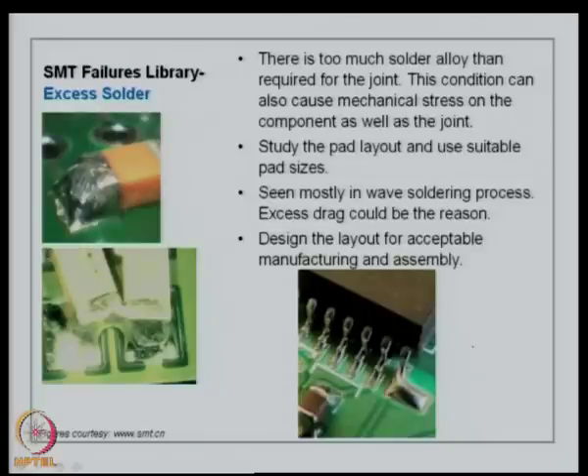The third one is excess solder. Here you can see in the picture different defects. You can see here too much of solder material, there is too much of solder there on the component. So, there is too much solder alloy than required for the joint. This condition can also cause a mechanical stress on the component as well as the joint. Too much of solder is also a problem. So, study the pad layout, use the pad size correctly, and use suitable volume of the solder paste material.